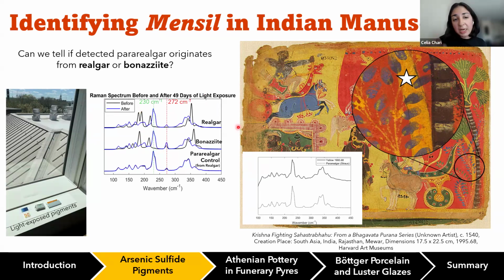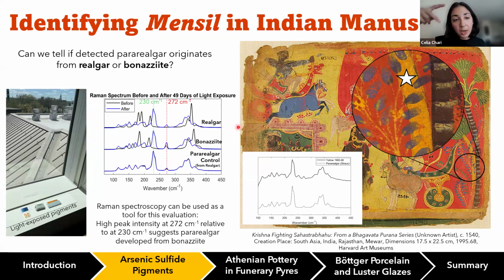272. One thing that I noticed repeatedly is that the ratios of the intensity of those two peaks can directly tell you whether that para-realgar came from bonazziite or whether it came from realgar. And I think that has to do with the fact that bonazziite itself already has a peak at 272. So there might be some residual, maybe not completely reacted parts of bonazziite that remain, causing that peak at 272 to be slightly larger.